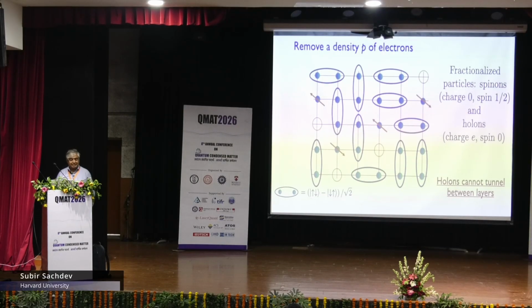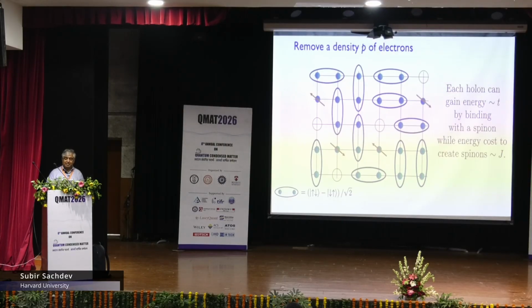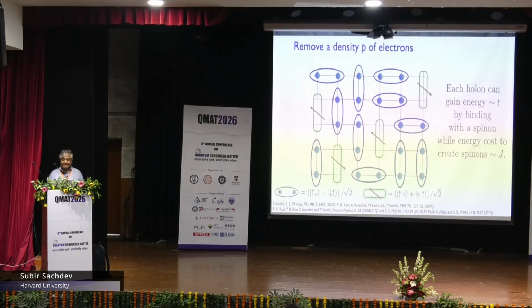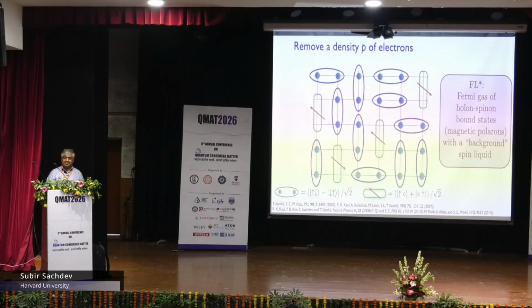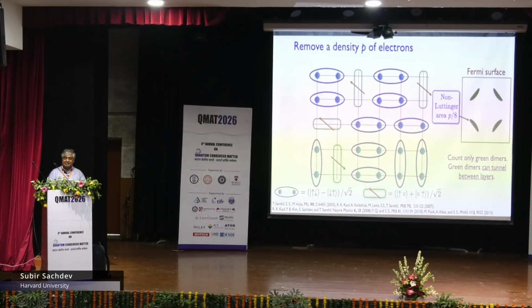But this is actually quite easily fixed. You can imagine that there's some attractive interaction between holons and spinons, and then they can form a bound state, which are these green dimers, and then the whole thing can resonate. So you have these bound states moving around, and these bound states have exactly the quantum numbers of an electron, and they'll form a Fermi surface. And so this is a very simple construction, at least by waving your hands a lot, of a metallic state where the Fermi surface encloses a non-Luttinger area, and our prediction was p over 8.